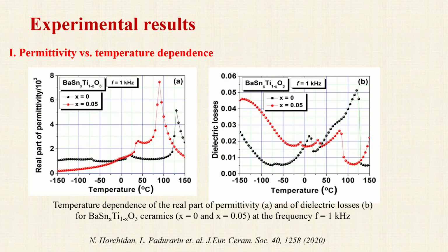The permittivity versus temperature measurements show that the samples are good dielectrics with tangent loss less than 5% in the entire temperature range from minus 150 degrees Celsius to 150 degrees Celsius. The transition temperatures are characterized by maximum values of the permittivity, respecting the general trends described by the Landau theory, as increase of the rhombohedral to orthorhombic and orthorhombic to tetragonal phase transitions and decrease of the Curie temperature in solid solutions.